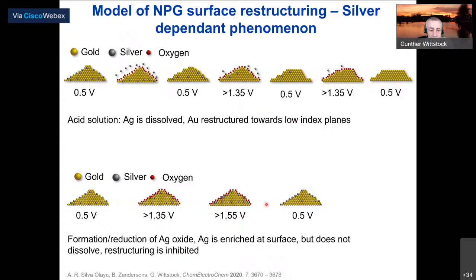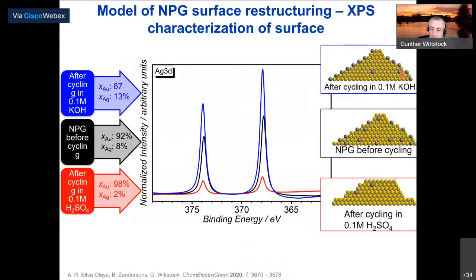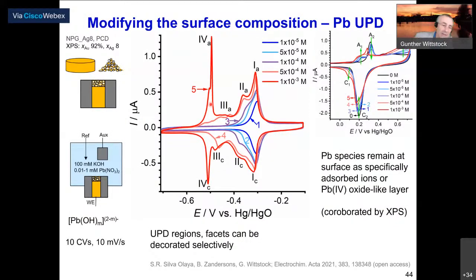If we do that in an alkaline solution, we just cycle the silver and form a silver oxide layer, which is then reduced, but the silver stays on the surface. And that has a very important effect because the silver stabilizes these high energy defects at the surface, whereas if the silver is removed, then the first surface starts to restructure and forms larger terraces of low index single crystal planes. So that is also seen in XPS here. So if we cycle in sulfuric acid, the surface concentration of silver goes down. That's the one of the starting material, and that is after cycling in alkaline solution, which pulls more silver to the surface. But that's not all.